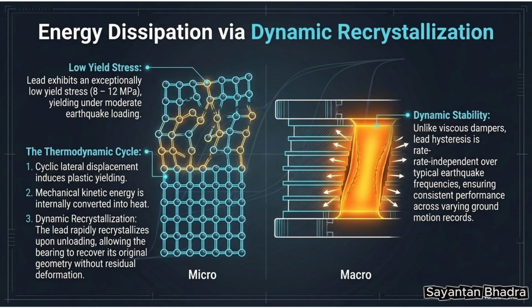Because the crystal structure of lead dynamically recrystallizes at ambient temperature during the unloading phase, the lead core recovers its initial grain geometry without exhibiting low-cycle fatigue or permanent structural degradation. Furthermore, unlike velocity-dependent viscous dampers, lead hysteretic response is rate-independent across standard earthquake frequency bands, providing consistent energy dissipation under variable ground motions.